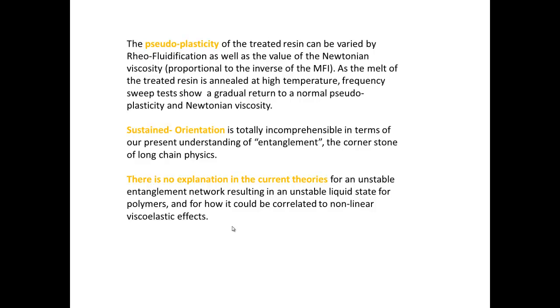I'm reaching the conclusions. The pseudoplasticity of a treated resin can be varied by rheofluidification, as well as the value of the Newtonian viscosity, which is, as we know, the inverse of the MFI. As the melt of a treated resin is annealed at high temperature, frequency sweep tests show a gradual return to normal pseudoplasticity and normal Newtonian viscosity. Of course, when there is some degradation, the so-called normal Newtonian viscosity is lowered. But we know from viscosity how the degradation is affecting the viscosity, and we cross-reference that with a GPC study.